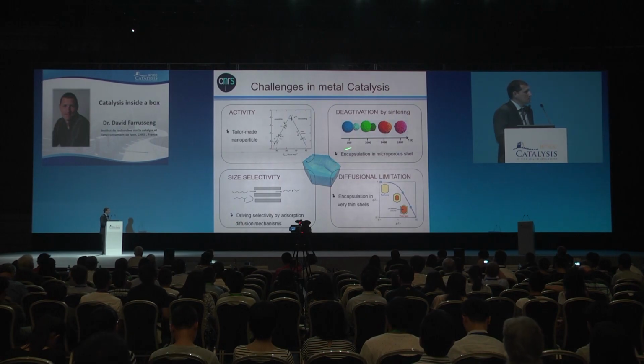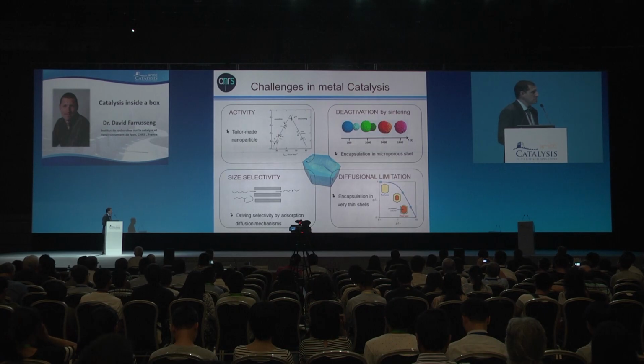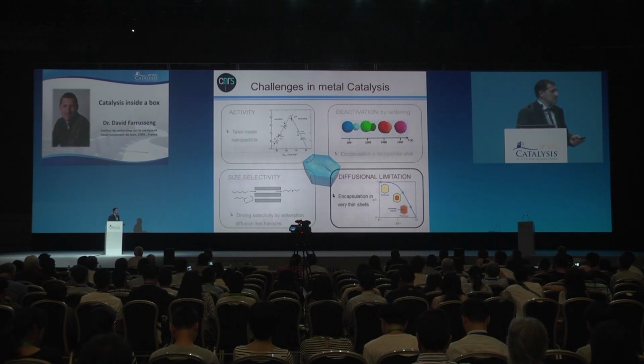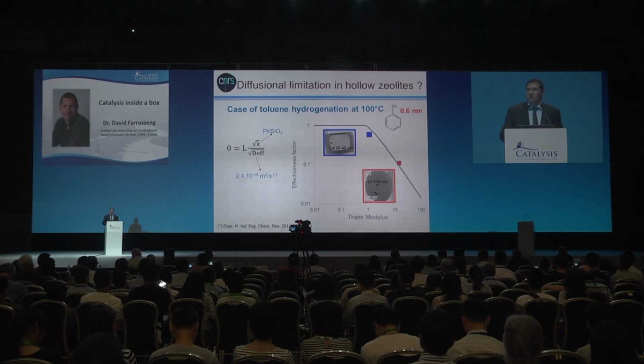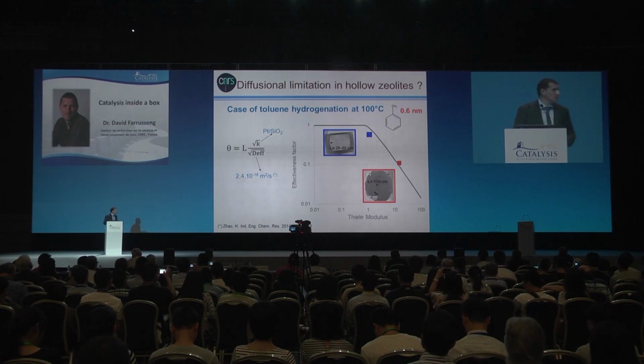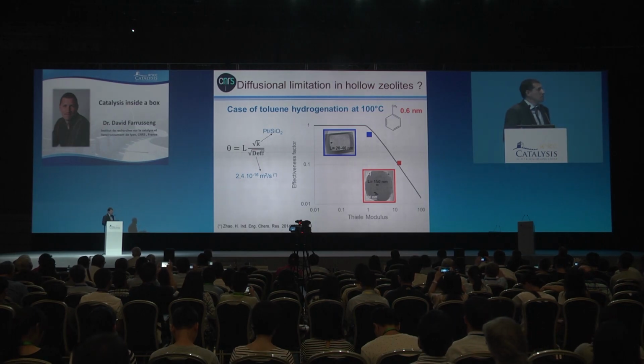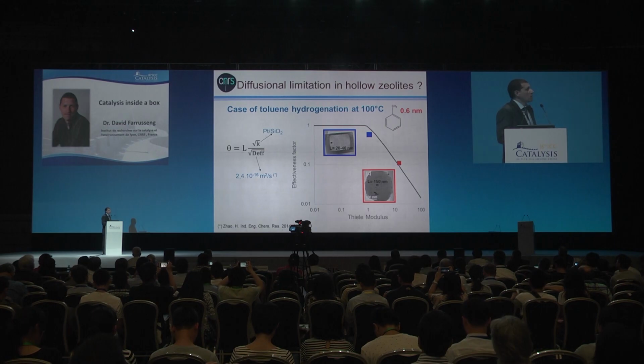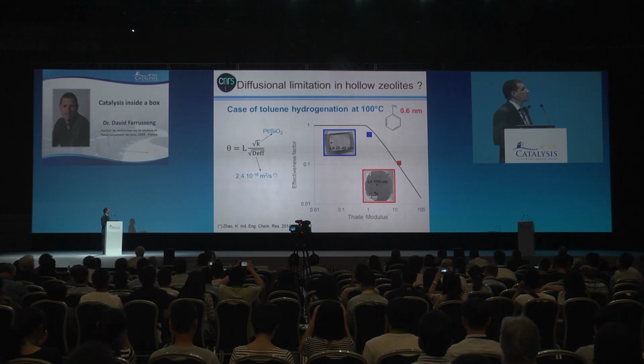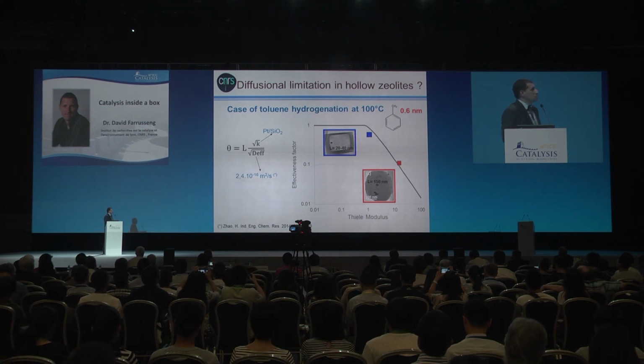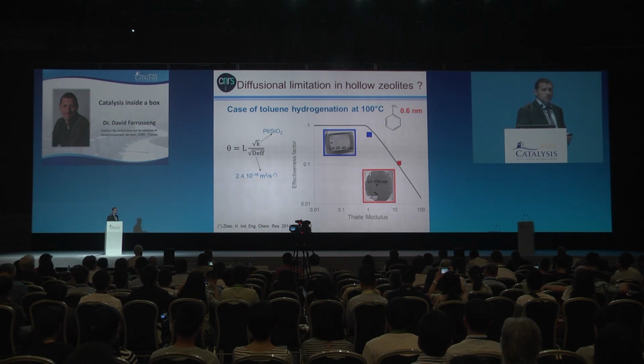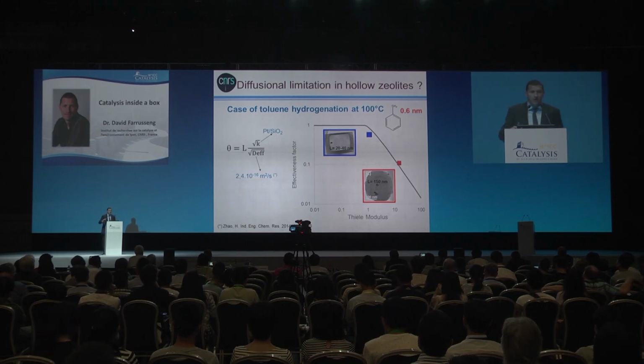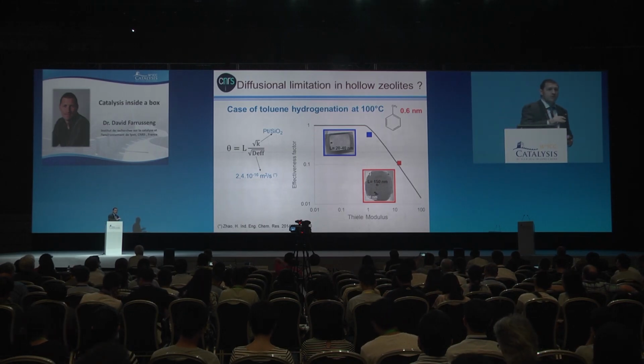Now I'm going to give you a few words on diffusional limitation, because it is known that the diffusion in zeolites is extremely slow, and I want to give you here the worst case scenario, so to say. I've taken the example of the toluene hydrogenation because toluene is a quite large molecule and has a hard time, so to say, diffusing in the zeolite.